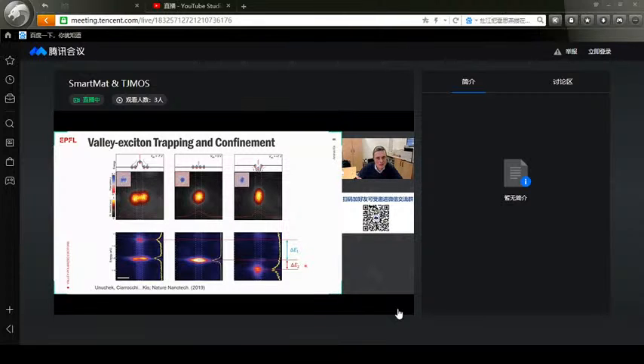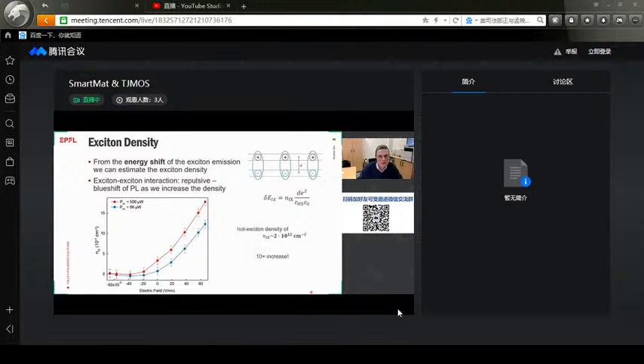And the way we can estimate the density of excitons is that if you squeeze the excitons in one place, because they're electrical dipoles, squeezing them costs energy because they would like to repel each other. So the difference between these two voltages, even though the voltages are the same in magnitude, but they're opposite in signs, you're going to create different energy shifts. And the difference in these two energy shifts actually tells us how many excitons we managed to confine in this region. And from this, we can see that we can actually increase the initial exciton density by a factor of 10.